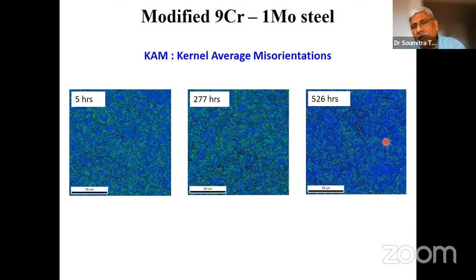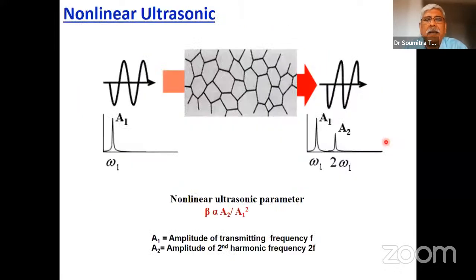And they can be revealed through electron backscatter diffraction studies to give you kernel averaged misorientation. And when you quantify this kernel average misorientation, you find that there is a progression. It may not be apparent to the eye, but I'll show you in a graph that there is a change. And concomitantly, simultaneously, we measured the nonlinear ultrasonic response of the material. So we are passing an ultrasonic wave of a particular frequency, and we are looking at the harmonics that are generated and quantifying the harmonics by the beta factor.